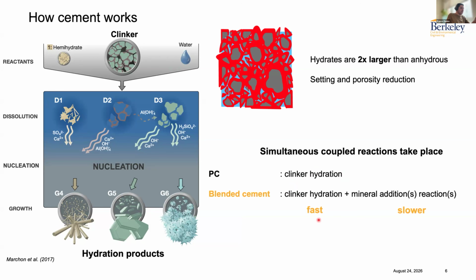because in addition to the clinker reaction, which in general, from a kinetic standpoint, we can deem as a fast chemical reaction, we have the chemical reaction of all of these mineral additions or supplementary cementitious materials that we may want to add into this blended cement to reduce carbon footprint, that are in general slower. And it's important to realize that all the chemical reactions that take place follow this same pathway of dissolution and reprecipitation. However, the kinetics are different, and in many cases, reactions are coupled to each other. For example, a pozzolanic reaction cannot take place until we have a sufficient amount of alkalinity in the system in order to get that pozzolanic reaction going. So there is a hierarchy that needs to be respected in how these processes take place over time.